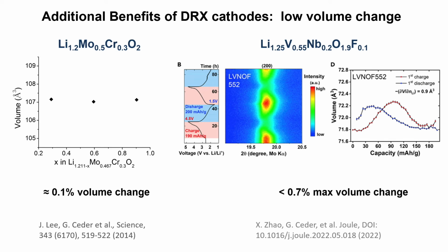Okay, there are some additional benefits that we had not anticipated. Disordered rock salt cathodes often have very low volume change. These are remarkable materials, the molybdenum chromium, here's a vanadium one, where you can take essentially out half the cations, you can take 1 lithium per formula unit out, and there is zero dimensional change. The dimensional change is below 1% in volume, which means in the lattice parameter, it's like 0.3%. So these materials are of interest for solid-state batteries, where you have mechanical contact between all the solids. You really don't want to have any interfaces that move around.